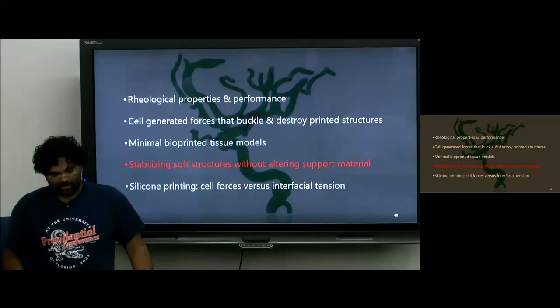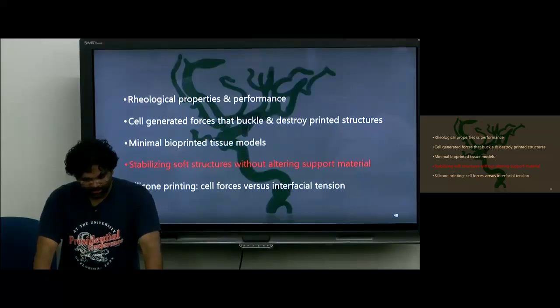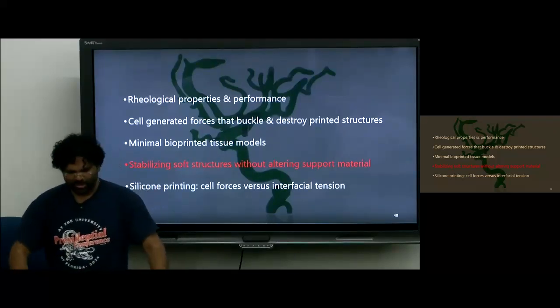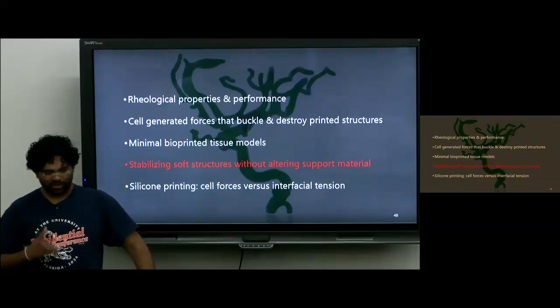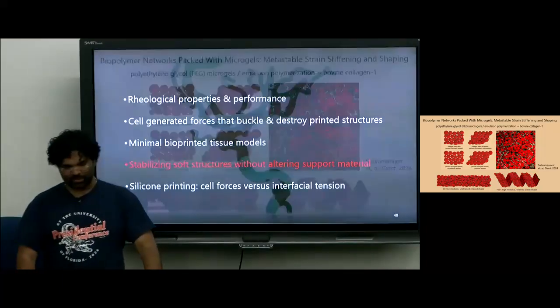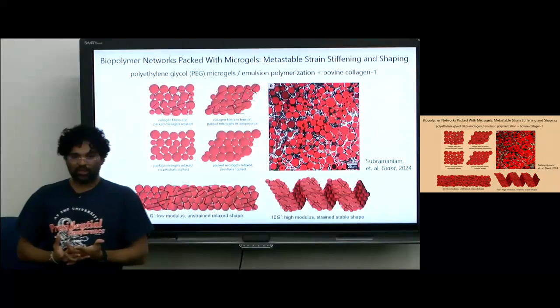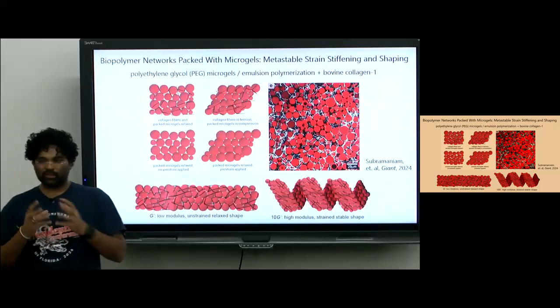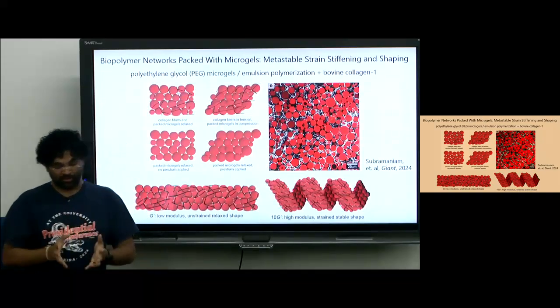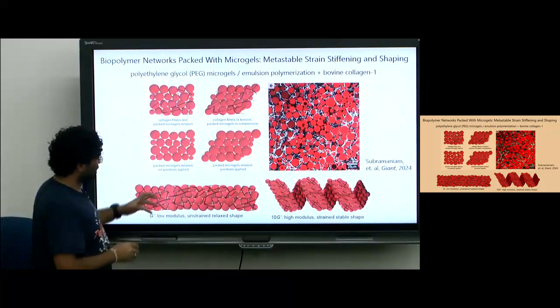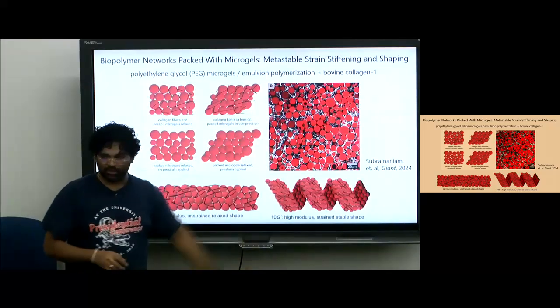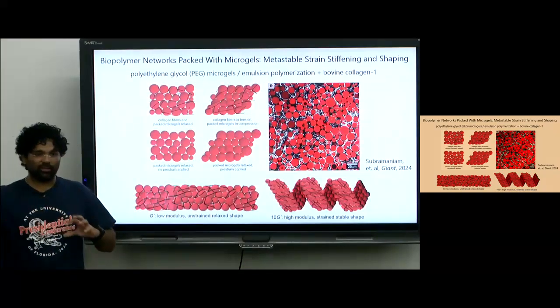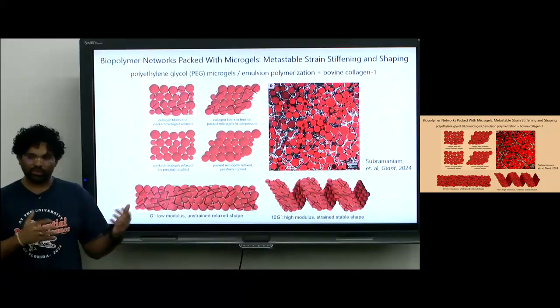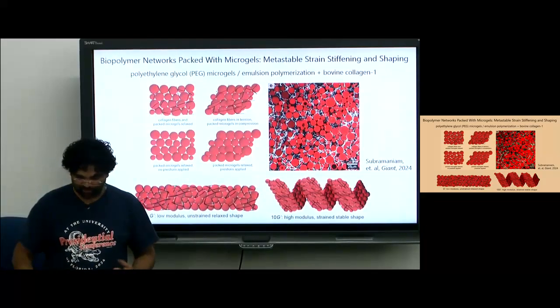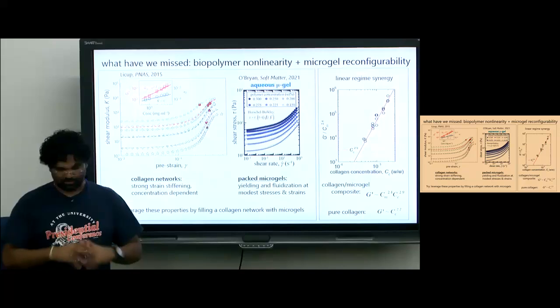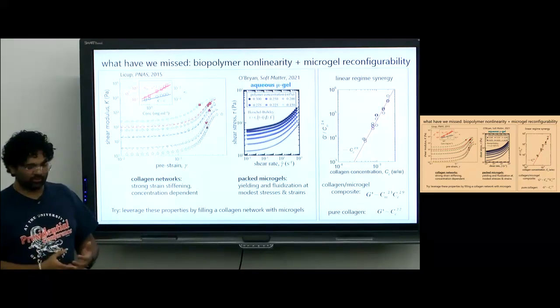And there was another work that I did, which is how we can stabilize soft structures without messing around too much with the soft material. In this case, I made a composite material of the collagen matrix with these spherical microgels, and they showed really cool behaviors. When we mixed the two materials together, the combined modulus of this composite jumped 10 times compared to what the individual components would have. And that was kind of unseen in any soft materials so far.